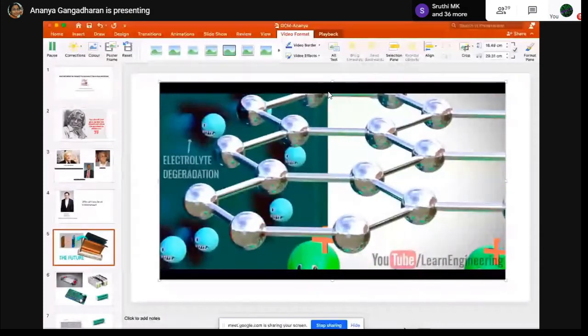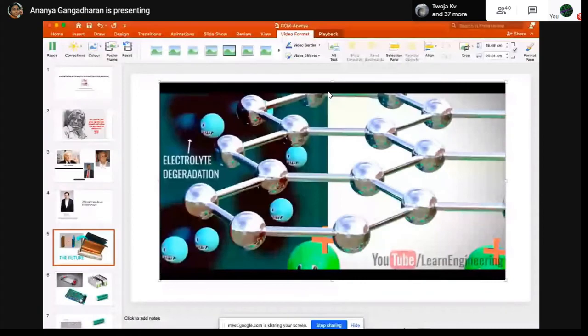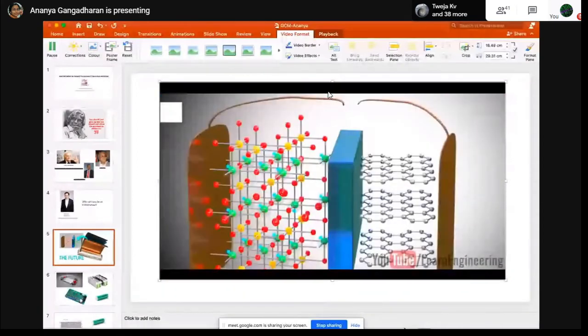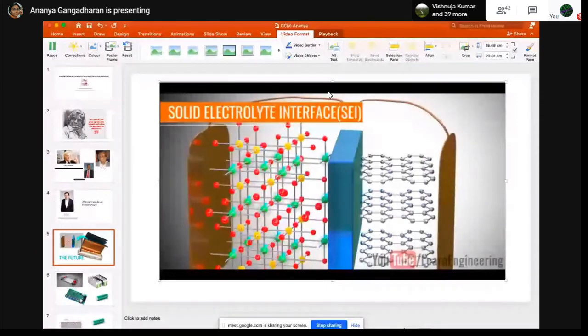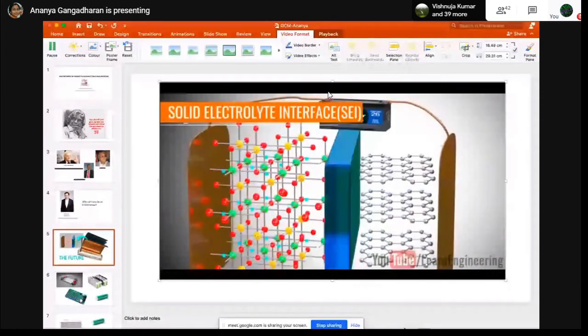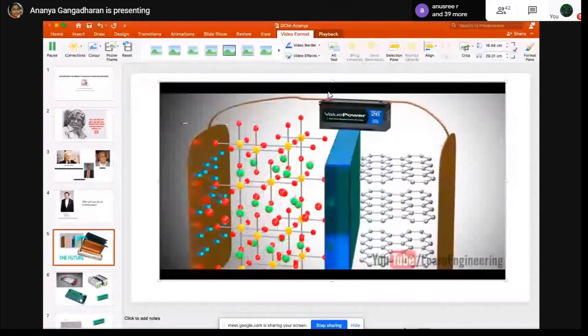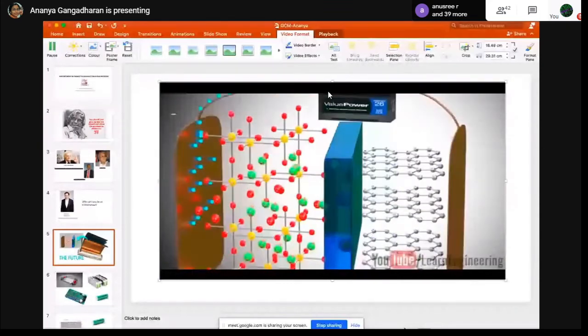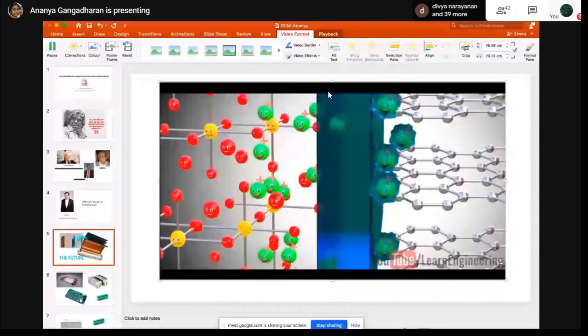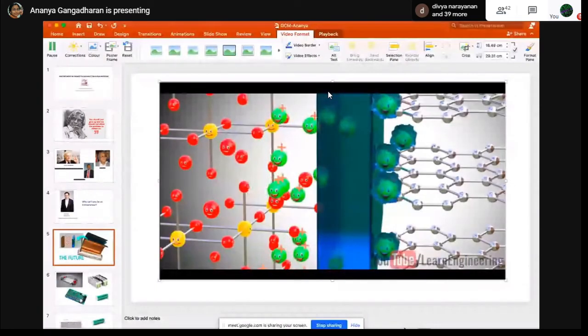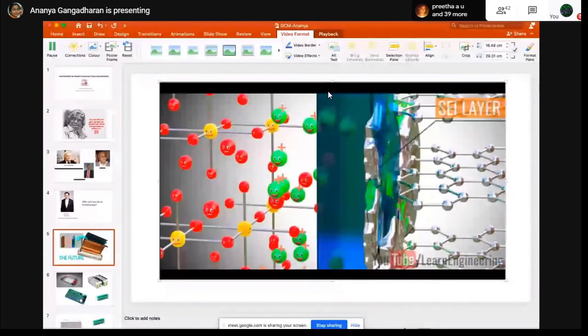However, the electrons never come into contact with the electrolyte due to an accidental discovery, the solid electrolyte interface. When you charge the cell for the first time, as explained above, the lithium ions move through the electrolyte. Here, in this journey, solvent molecules in the electrolyte cover the lithium ions. When they reach the graphite, the lithium ions, along with the solvent molecules, react with the graphite and form a layer there called the SEI layer.